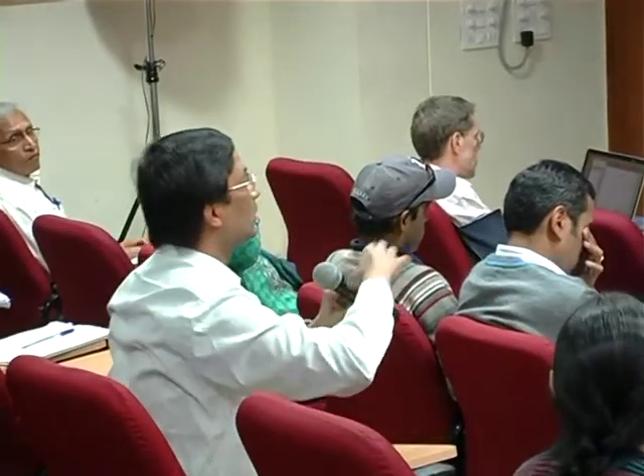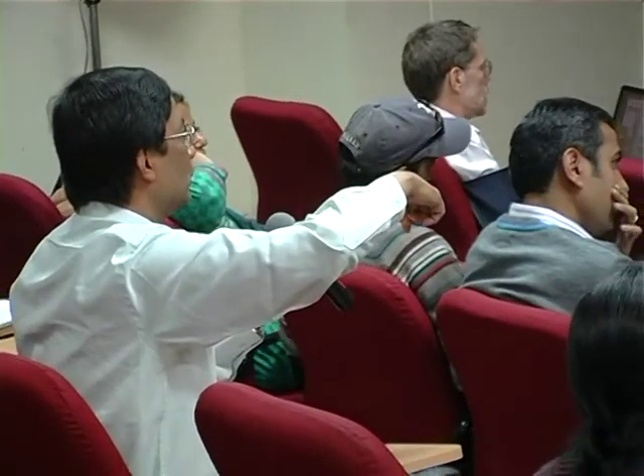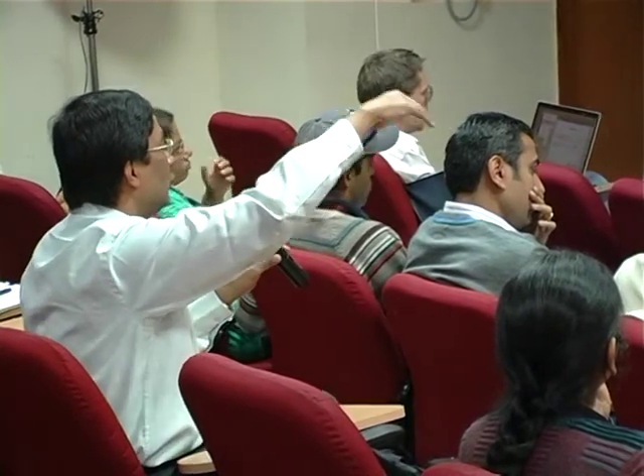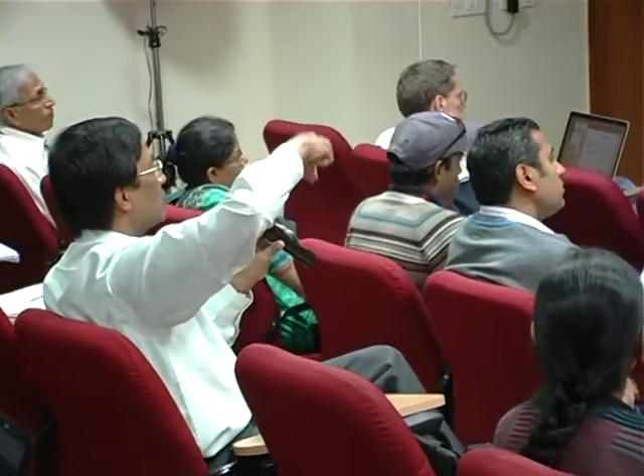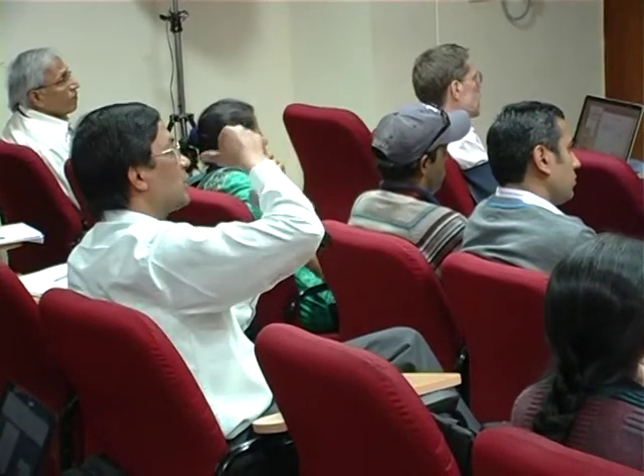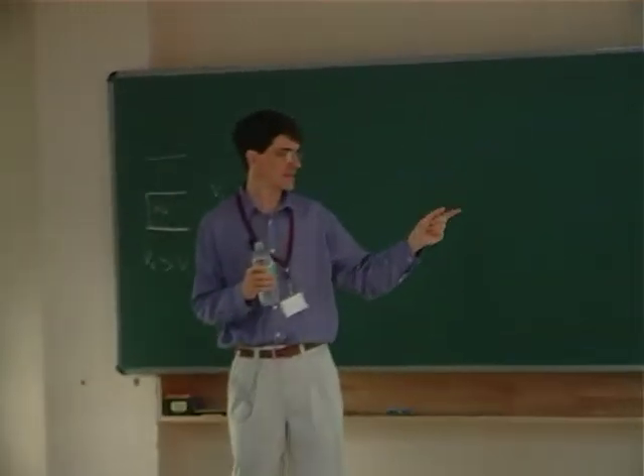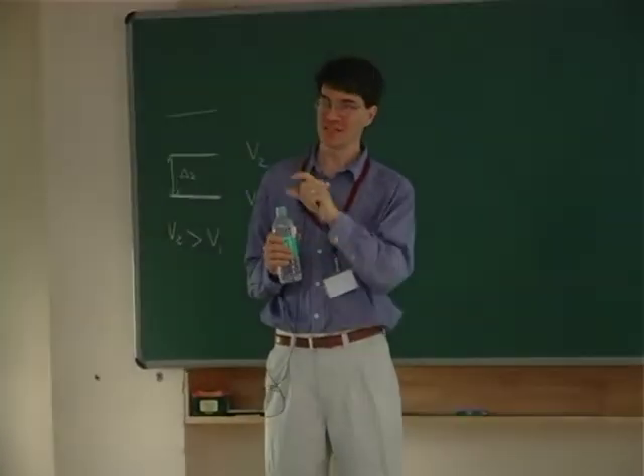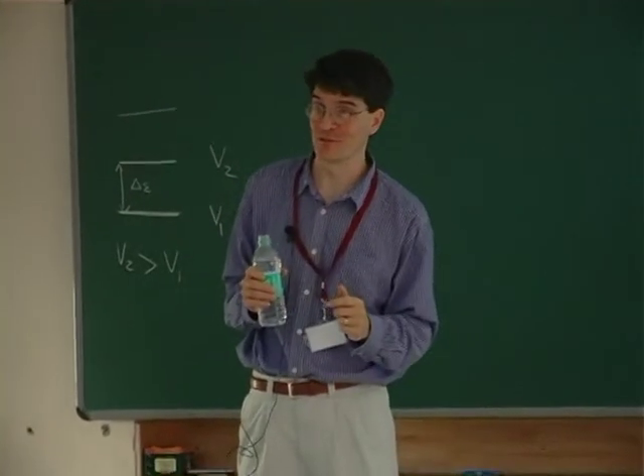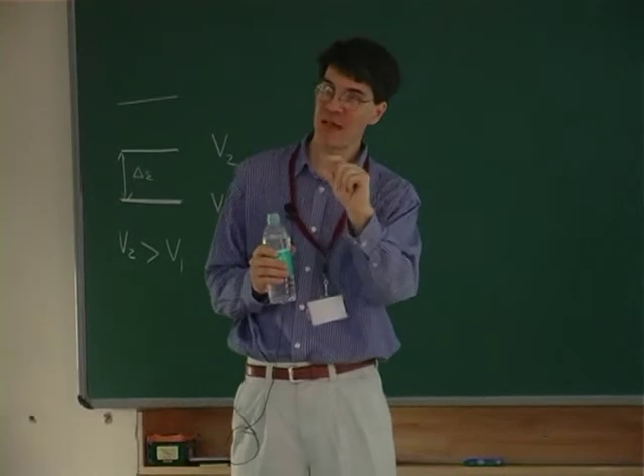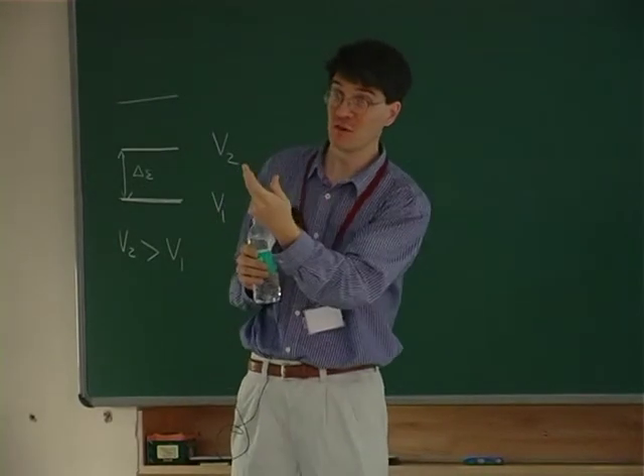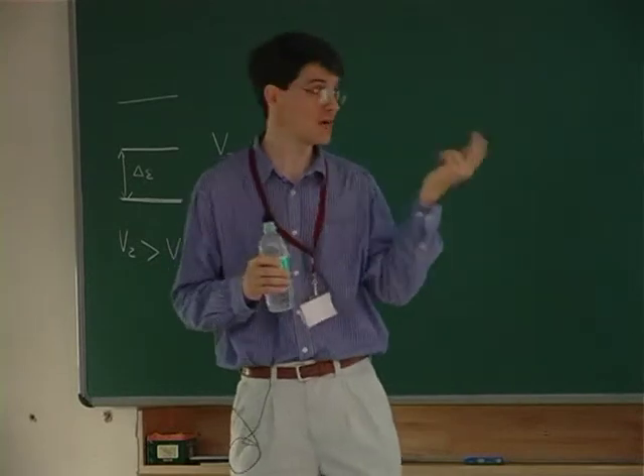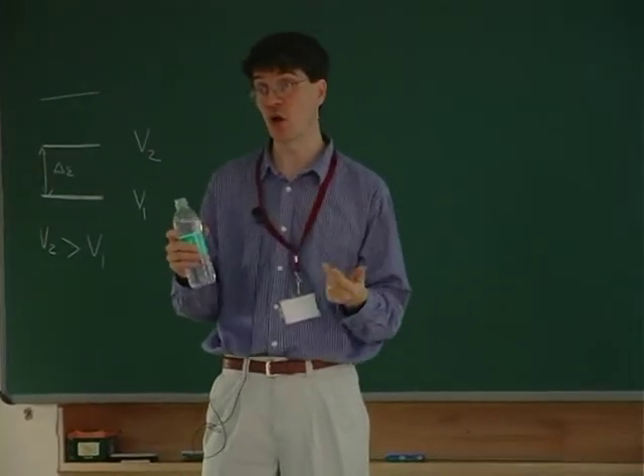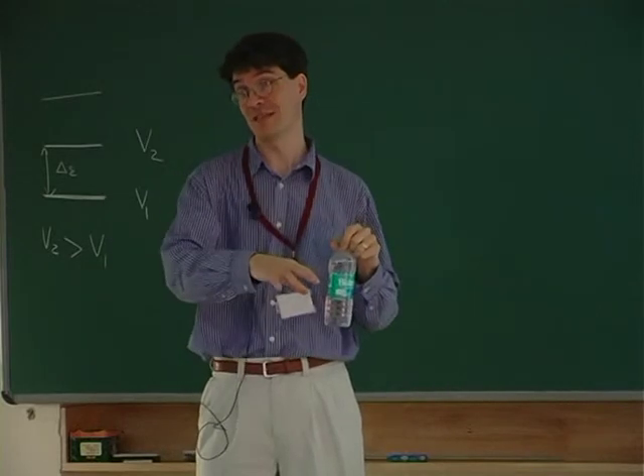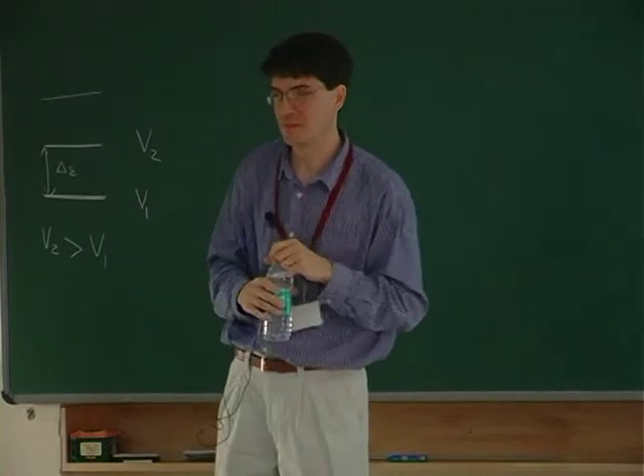Maybe it's more to do with not the lateral dimension, but the depth into which you're probing, because I don't know how deep into the system the laser is exciting, where your X-ray penetration depth could be different. This is why films are great. The film was 35 nanometers, and the extinction depth of the light was 30 nanometers, so it was wonderfully well matched. Because we're measuring just the film, you're right. If we tried similar experiments in bulk materials, those are very hard. Exactly, that's what I had in mind. You're probing mostly the bulk that's doing nothing. And so the lateral matching is easy, but the depth is hard.